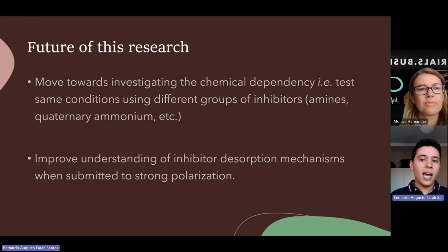That is, whenever you already have the surface covered with corrosion inhibitor, so the inhibitor is already adsorbed on the surface, and you may suffer some kind of, I don't know, oscillation in the potential, or even be polarized, and that inhibitor will dissolve from the surface. So it's a similar understanding. It's not the same thing, but it's similar to what we see with stainless steel with the passive layer.